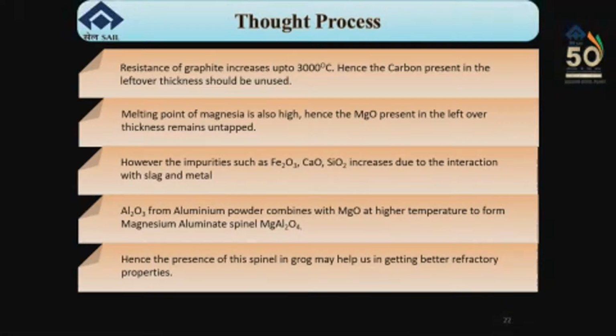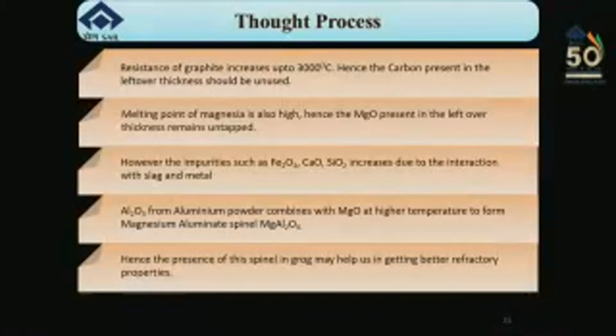Now, before going for this study, the thought process that we were having is that the resistance of graphite increases up to 3000 degrees Celsius. Hence, the carbon present in the leftover thickness should be unused. Melting point of magnesia is also high. Hence, the leftover thickness of the bricks remains untapped. However, the impurities such as iron oxide, lime, silica increase due to the interaction with slag and metal. Alumina from aluminum powder combines with MgO at higher temperature to form magnesium aluminate spinel, and this has very high refractory properties.